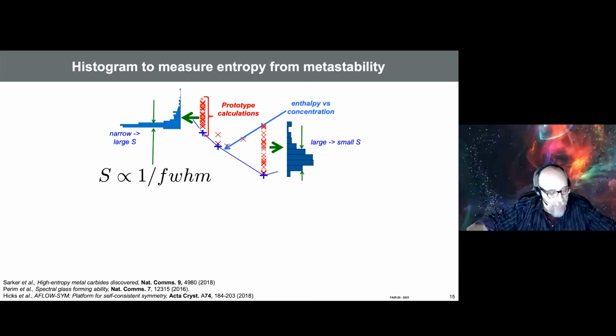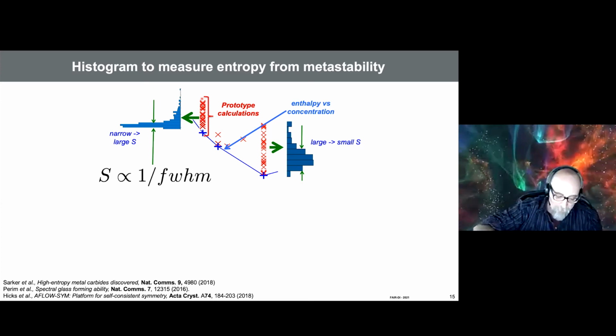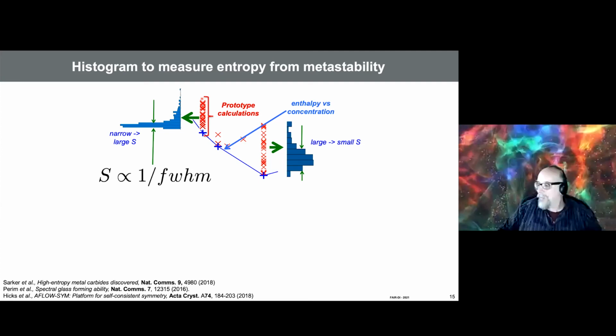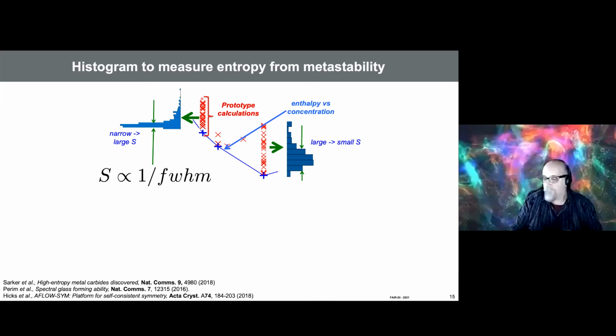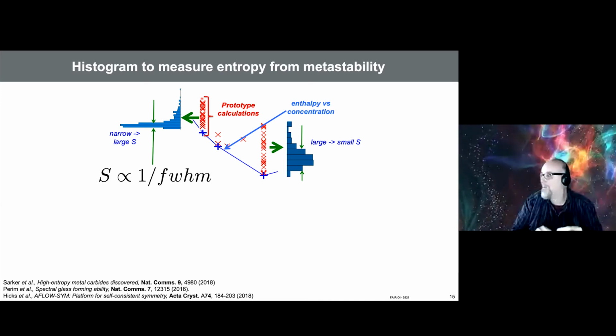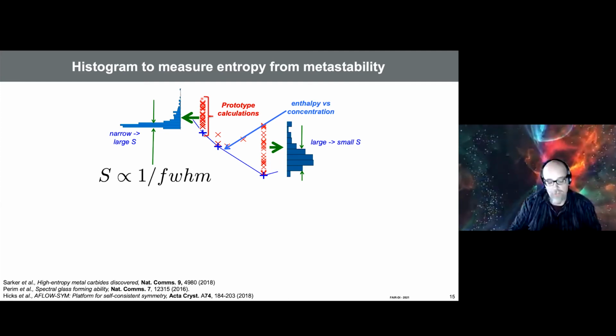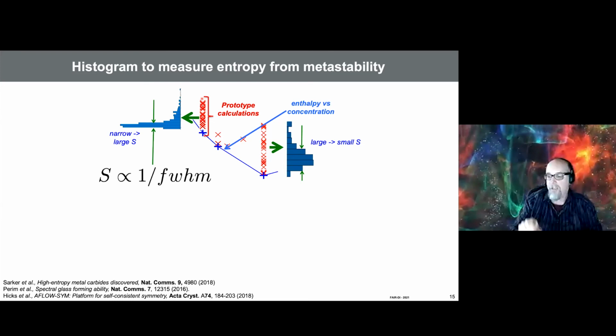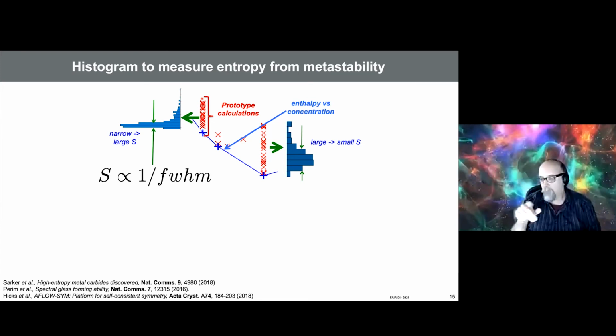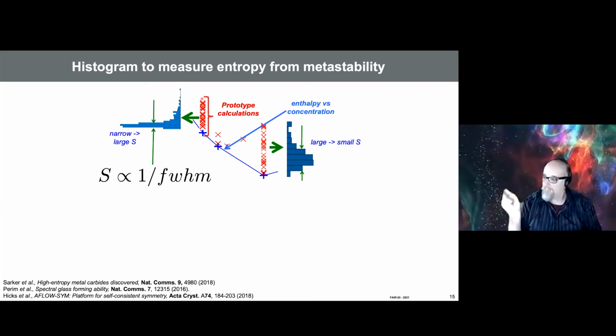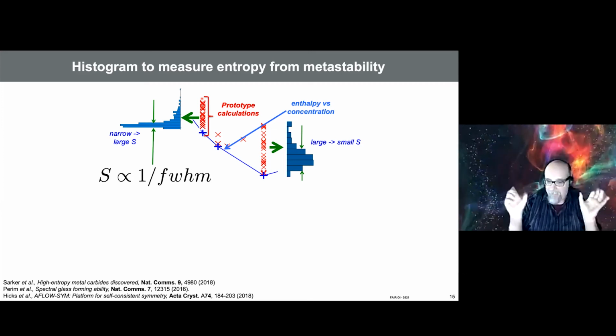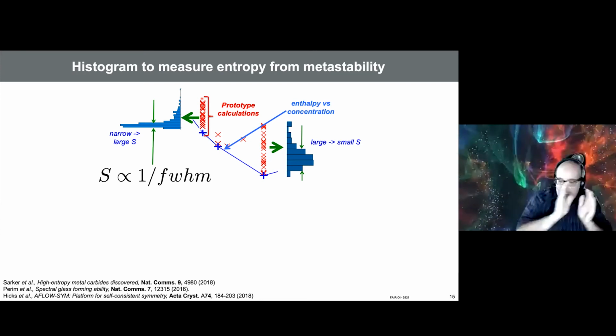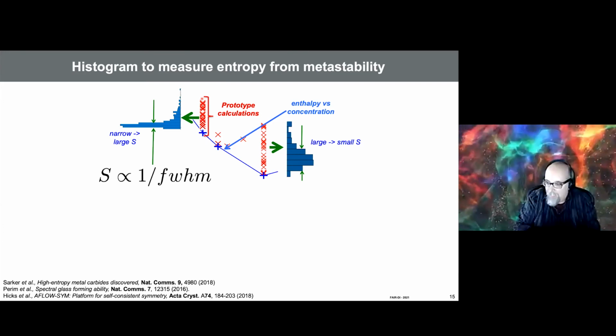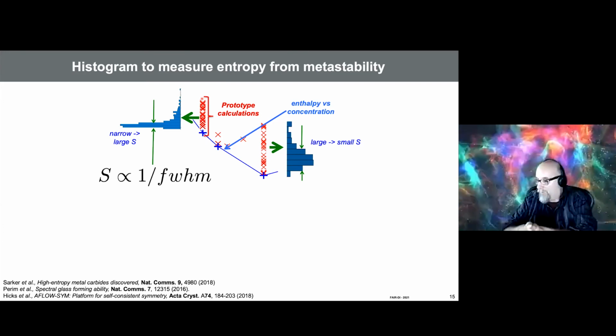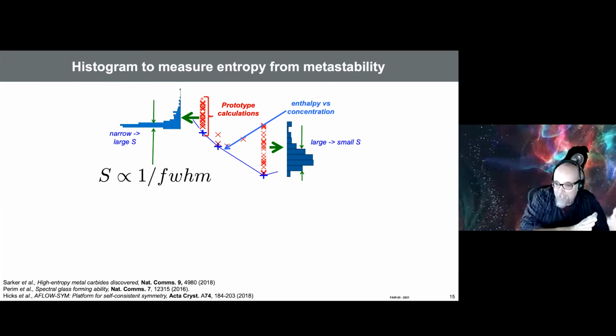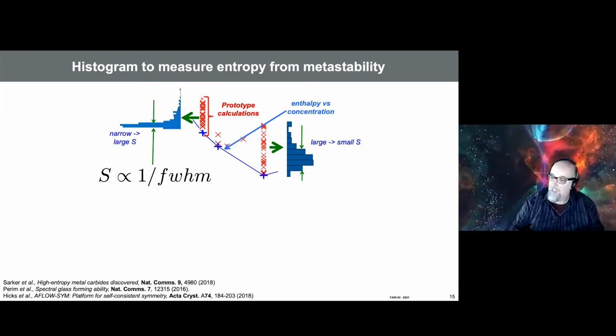Remember that Boltzmann said that the entropy is the degeneration of the states. But that's not really right. This is only if the states have the same energy. If the states have a more or less similar energy, then that is not a good definition, and you need to go to the Gibbs definition of entropy, which says that S(E)dE is k, of course, log of omega(E)dE. So you have this dE, which is the bin, the energy between E and E plus delta E. Once you have the number of states between E and E plus delta E, which is this omega, you take the log, and then you get S times dE. So you remove dE from both sides, and then you get this S.